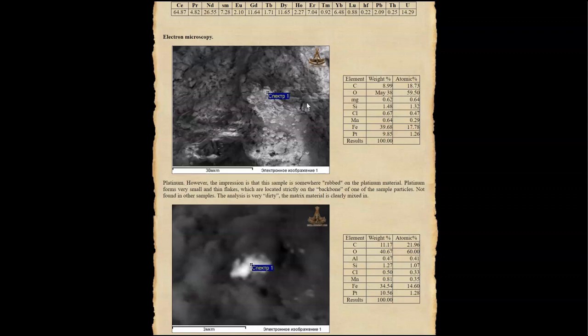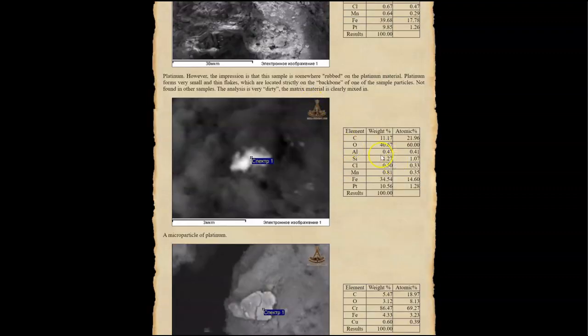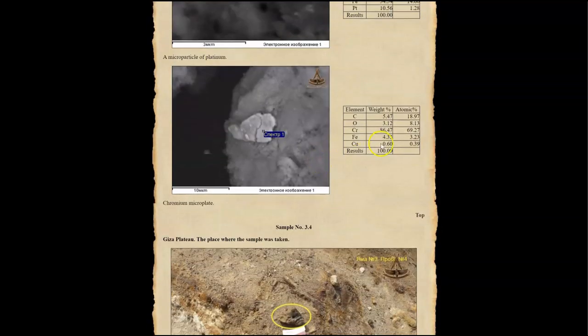So my question is, where the hell are these platinum flakes coming from? And another microparticle of platinum here at 10.56% platinum. And here, a fragment of chromium, 86% chromium. Very, very unusual indeed, and we will see more of this coming up soon.